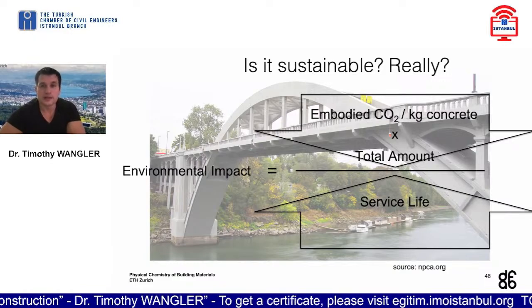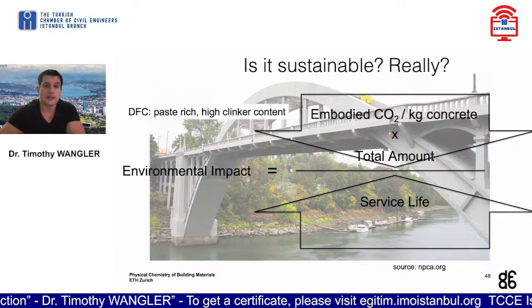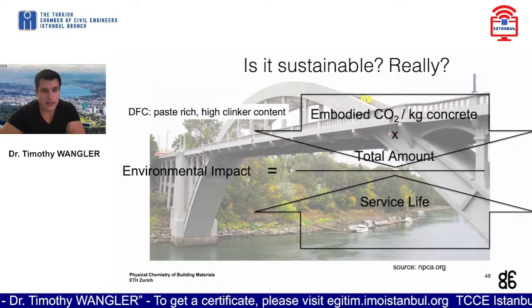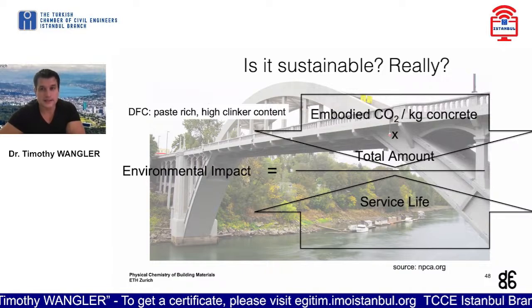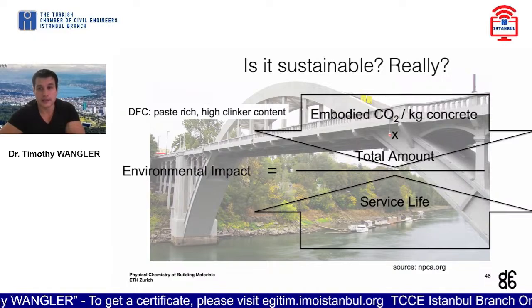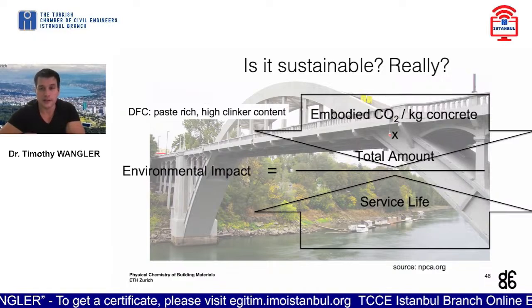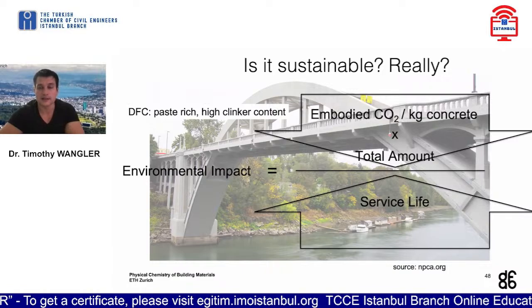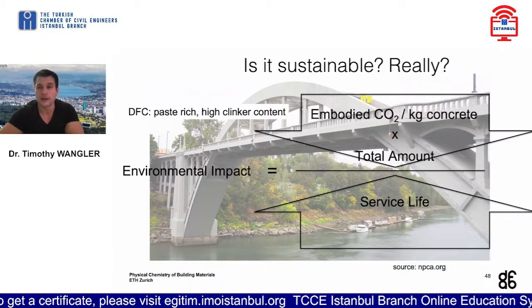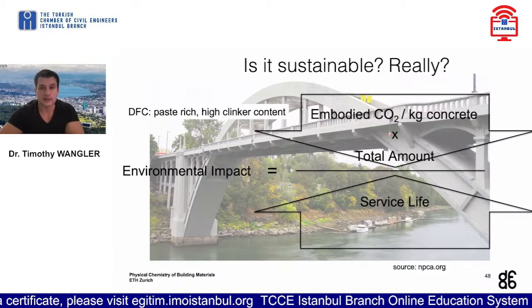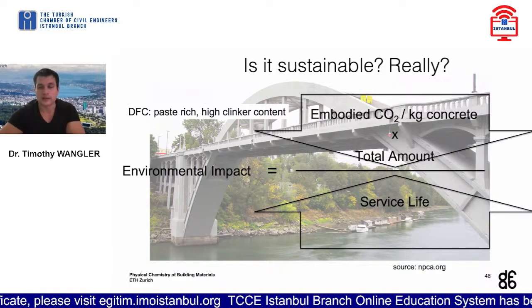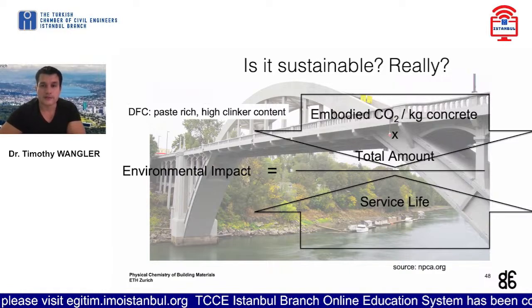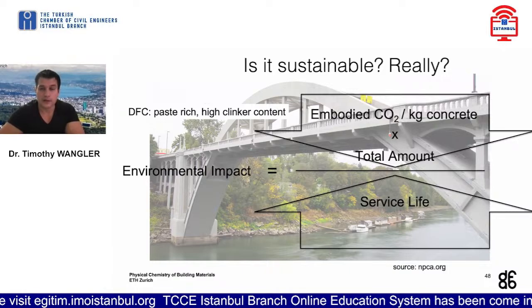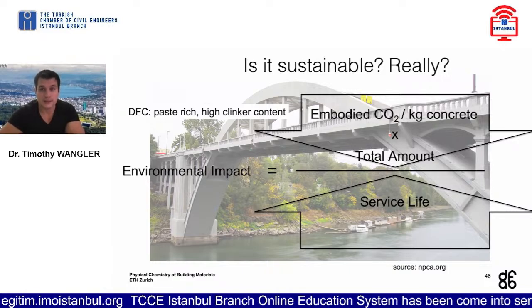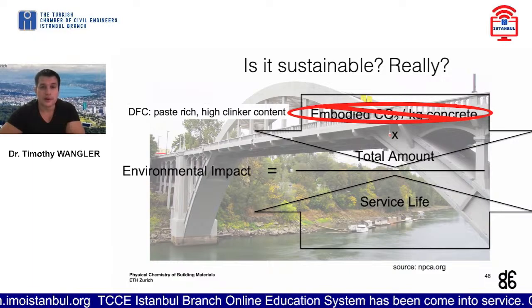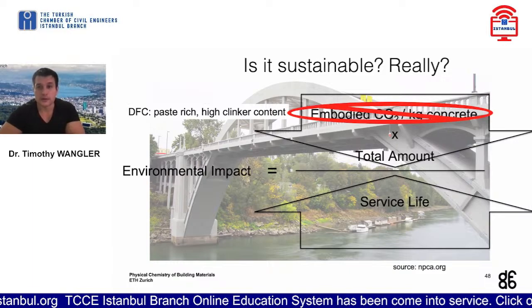And when it comes to digital fabrication with concrete, it turns out that we're using very, very high paste contents in our mixes and very, very high clinker contents overall. We have cement contents often in the range of 500 to 600. Even one of our first mixes had 800 kilograms of cement per cubic meter. So very, very high. And it's like this because of the processing. So I don't think that it's very sustainable with respect to this just yet.